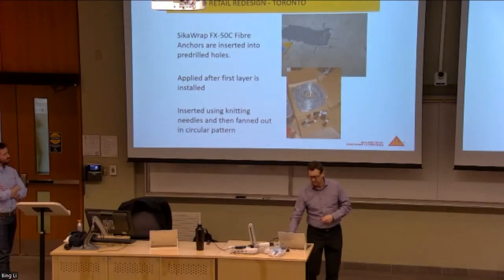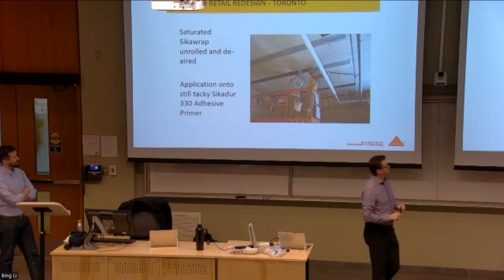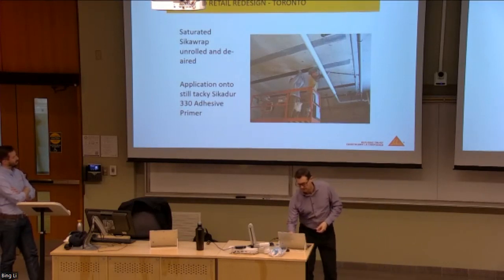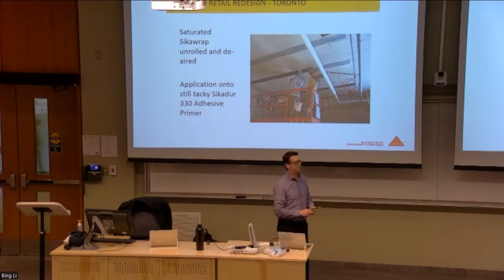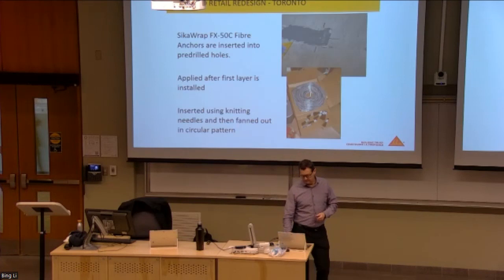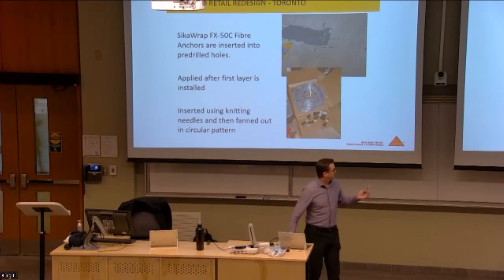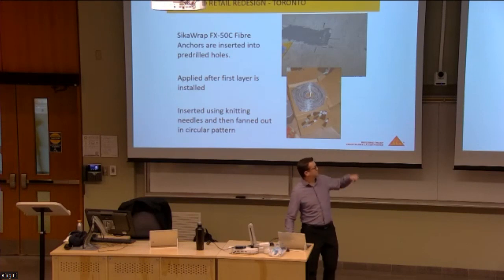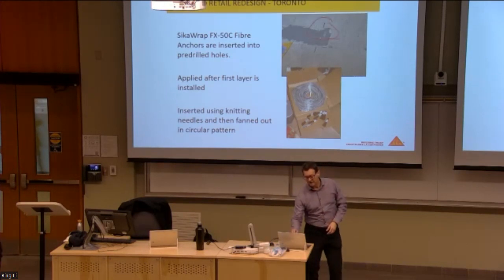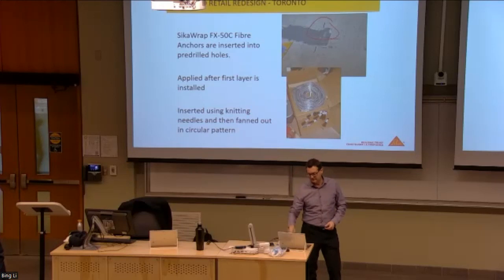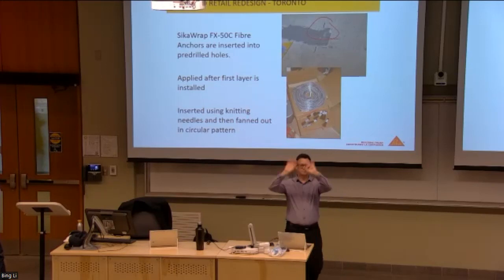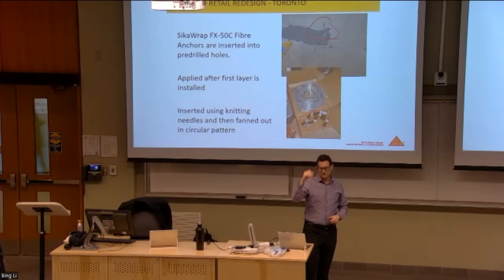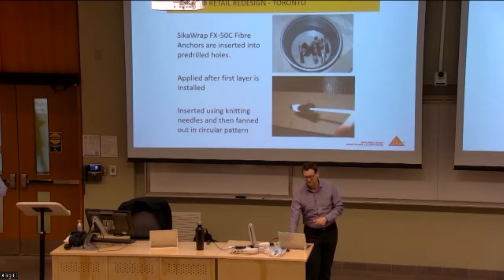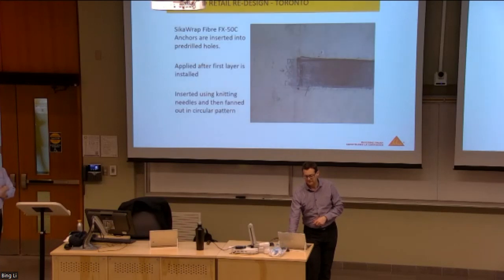Nope, never mind. So at the ends of this, the extremities in here, we want to resist the peeling forces that are inherent. And we do that with a stitching technique. I won't get into this too much in depth, but you can see the three lines that are taking place here. What's happened? There's a hole that was drilled into there. Once the fabric goes up, they basically take these small strips of the carbon fiber themselves and insert it into the hole and fan it out, and they marry the anchors into the fabric itself. Okay, so that's what's happening in that example.